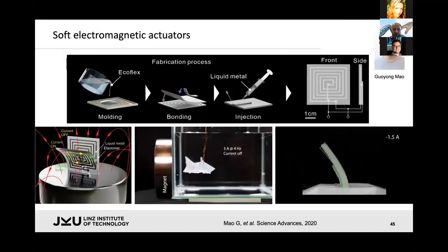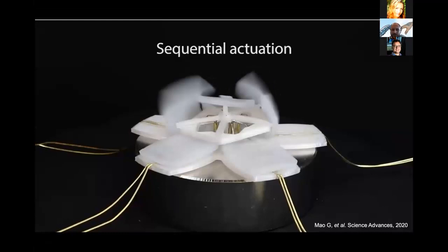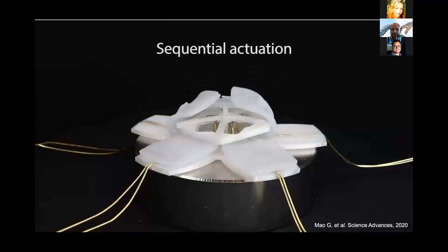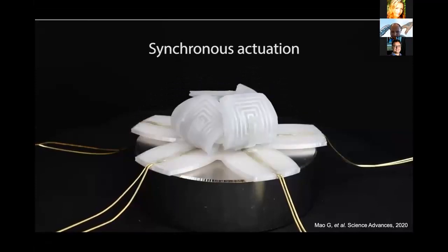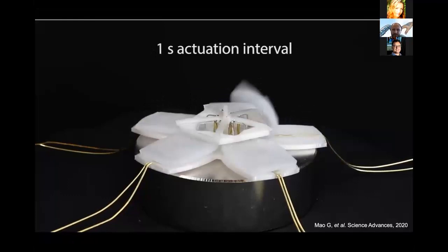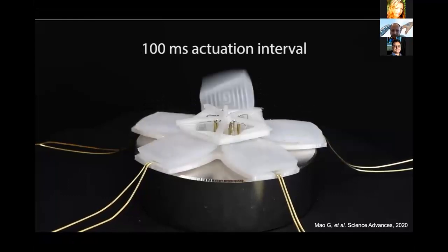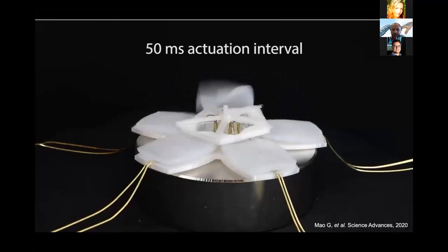We are doing a lot more with actuation, and another way of getting actuation in soft materials is by exploiting the Lorentz force. And my postdoc Johannes is pushing forward these topics, where he uses liquid metals embedded in an elastomer that are exposed to a static strong magnetic field, a static B field. And by applying a current, you basically have the Lorentz force acting on parts of these conductors, and you can get a very controlled and a very nice deformation in the actuators, and it's basically programmable. So you have sort of a way of programmable robotic matter here that is entirely soft and needs nothing else but very low voltages, well, currents in the ampere region, and the static magnetic field. So we are now working on miniaturizing this type of really, really fast and really controllable actuators.